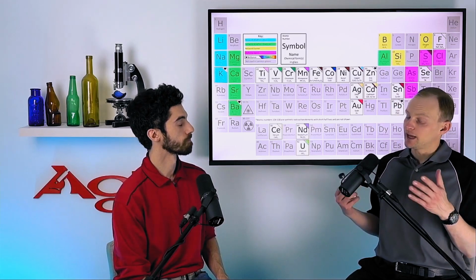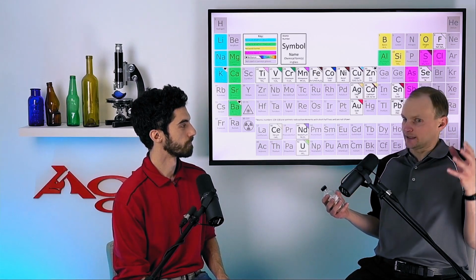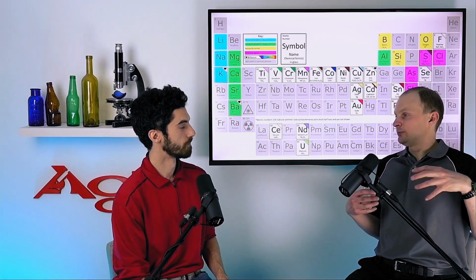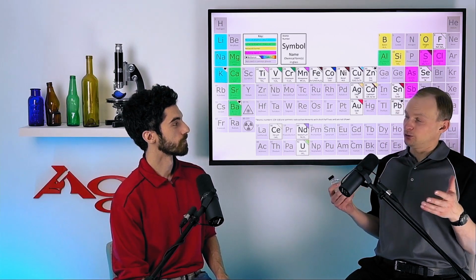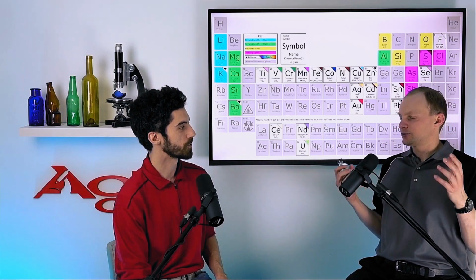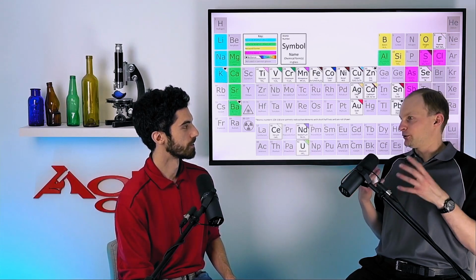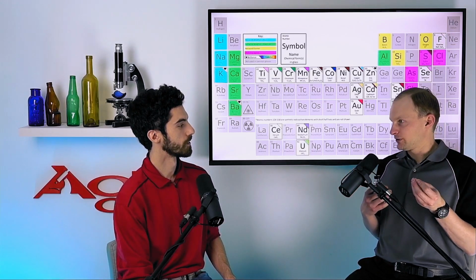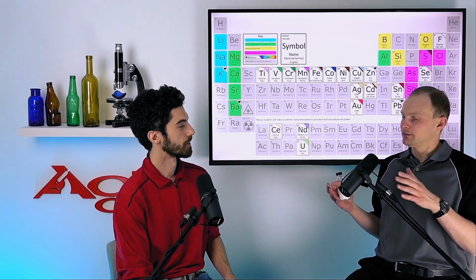This soda ash, though, this is one of the major innovations that allowed glass making to take place. You can make glass just out of pure sand. When lightning hits sand, it will make a glass. It's something called a fulgurite. But it takes crazy high temperatures to melt pure sand, so the pure quartz. There's reasons why you might want to do that. We could talk about that later.